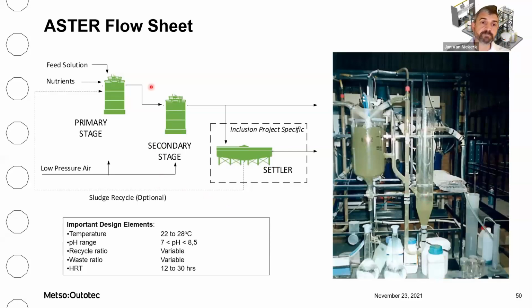The process is fairly simple. It normally consists of 1 or 2 stages of Aster tanks, followed by a settler that can be included if required by the process. Typical operating conditions are somewhere between 20 and 28 degrees C, neutral or slightly alkaline conditions, and hydraulic retention times of between 12 and 30 hours. Mild agitation is normally included in the reactors themselves, and a low volume of low pressure air is added just to maintain oxidizing conditions in the Aster tanks.